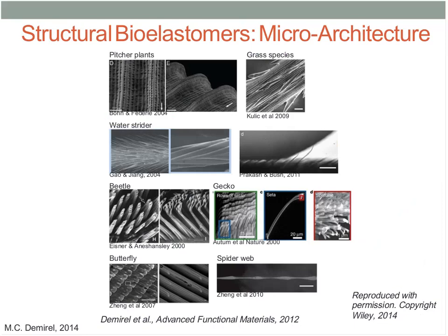Nanotexture surfaces composed of asymmetric structures are widely used in nature for wet and dry adhesion. Electron microscope images are shown in the slides of various structural features. Some insects employ a special form of wet adhesion by secreting adhesive fluids through arrays of setae to adhere to smooth or rough substrates. For example, the beetle uses such a technique to respond to disturbance by activating a tarsal adhesion mechanism. While defending itself from a predator, the beetle presses a surface with all its bristles to withstand pulling forces of up to 60 times its body mass for up to 2 minutes.